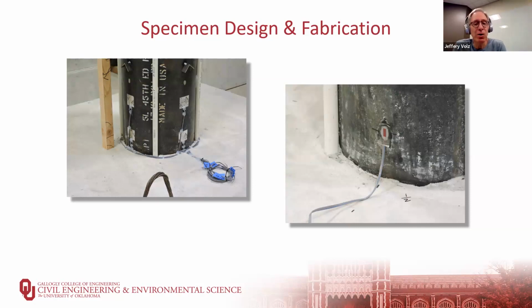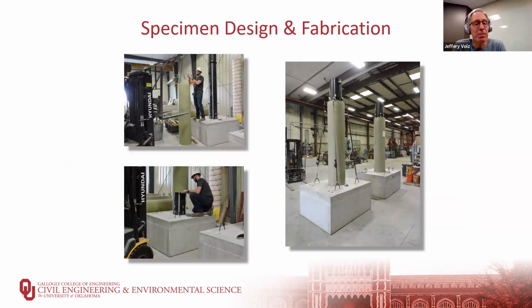Once the strain gauges were in place, we could lower the FRP tube into place. Now you can just use spacers to get the FRP tube centered about the steel tube, because the steel tube is locked in place now after the base foundation cures. And just spacers, the right depth spacers, can hold the FRP tube in place. But to make sure that it was anchored well, we also developed a halo system on the top and tied it down with some ratchet straps to get ready for placing the concrete in the core.